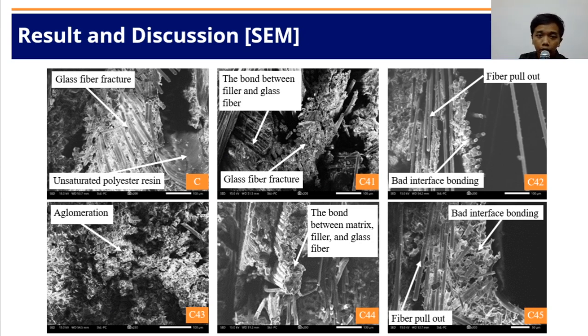The C41 composite shows a good interfacial bond between the glass fiber, matrix, and filler. This is in line with the result of the impact test that C41 has the best impact strength among the other filler specimens. The C43 composite has the lowest impact result among the other specimens. As we can see in this picture, it has been observed that in the C43 composite, there are areas of filler agglomeration that cause a decrease in impact strength of the specimen.